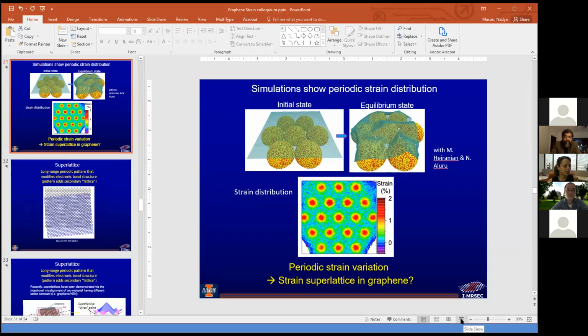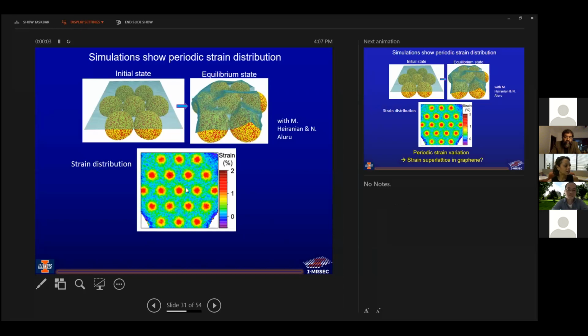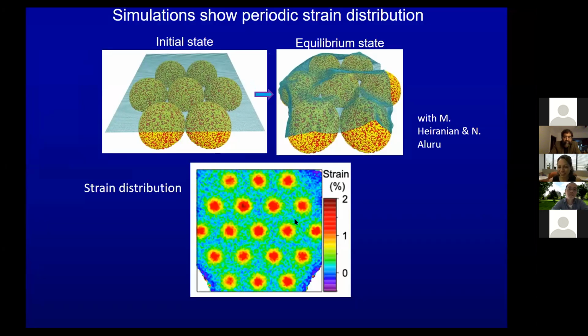I mean, that's how we, I mean, so, let me find this thing. This is the calculation, sorry, you can see it here. I mean, you can see it, right? So this is basically how it's calculated. And so you can see both of your questions sort of answered here, is that the calculation is a couple percent strain at the top of the spheres. And it looks like it's relatively, okay, this is theory, and I believe their spheres here were 10 nanometers in size. Maybe there are 10, maybe there are 20, but you can see it's localized over maybe 5 nanometers. But we have 20 nanometer spheres, so yeah. 5 nanometers is a significant fraction of 20, yes. Right? So this is what we guess that the strain profile looks like approximately.